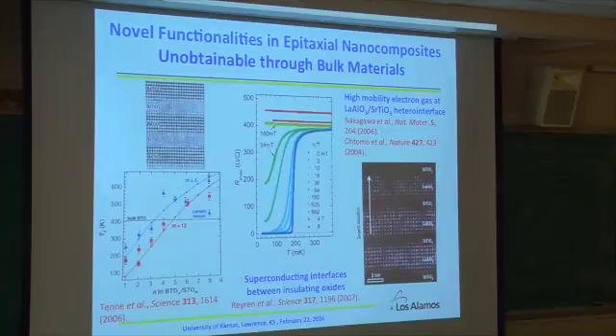Another example of a superlattice: lanthanum aluminate and strontium titanate. Both of these materials are insulating. But when you put these two together, depending on how you terminate the interface, you can change it to a superconductor. Across the interface, you form a 2D electron gas. Again, several groups, from Stanford and others, show that depending on how you do it, you see either insulating or superconducting behavior. So many things you can do: by controlling the interface, you can really control the functionality.